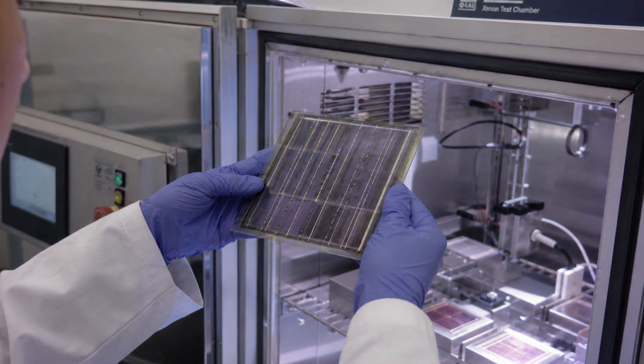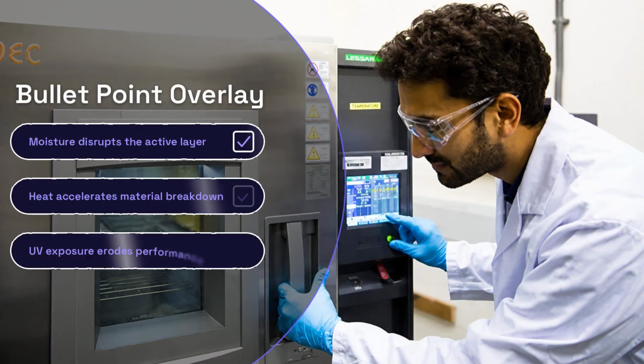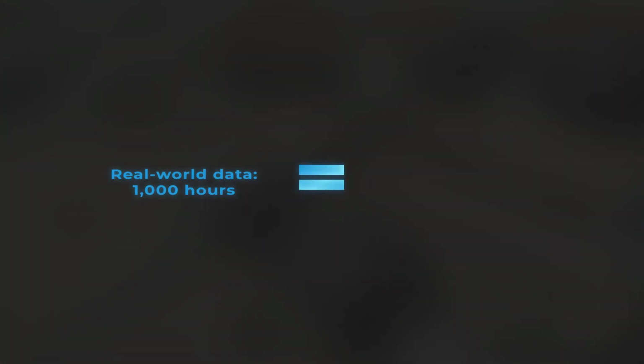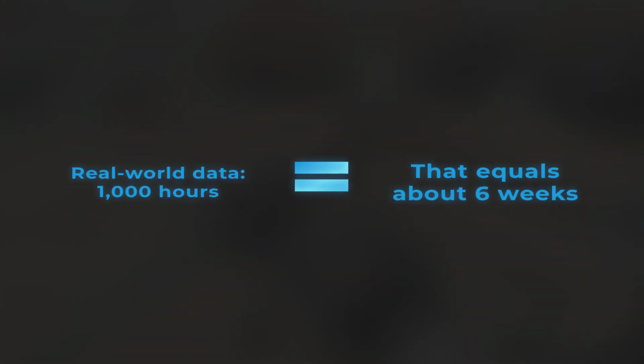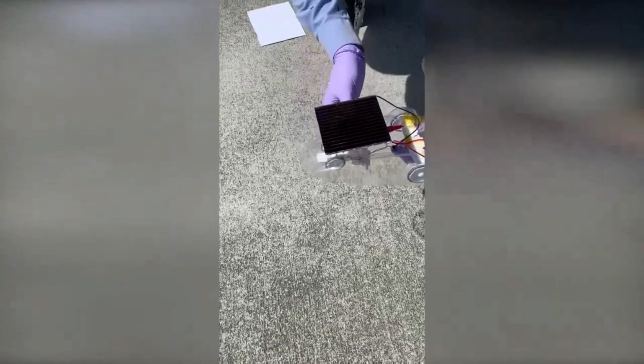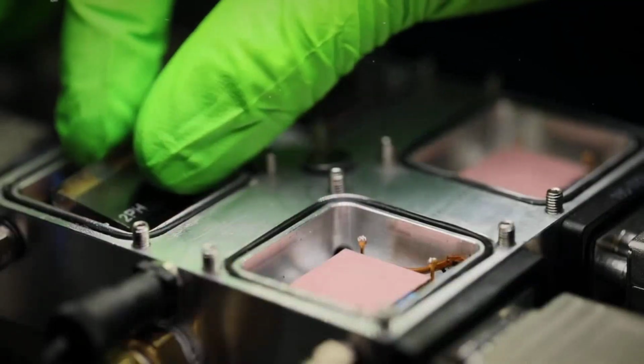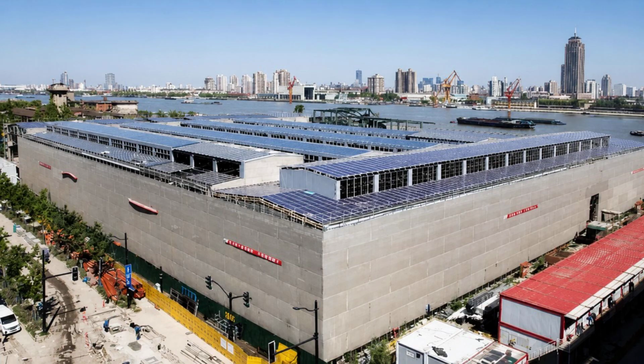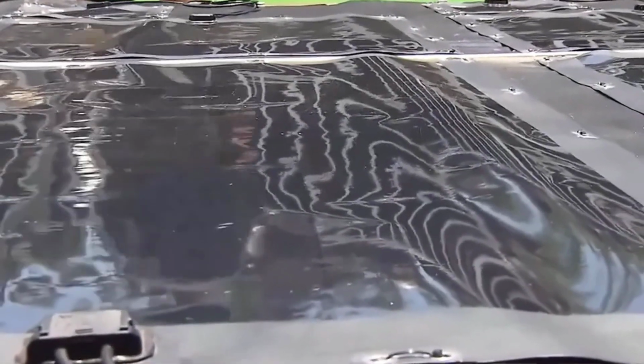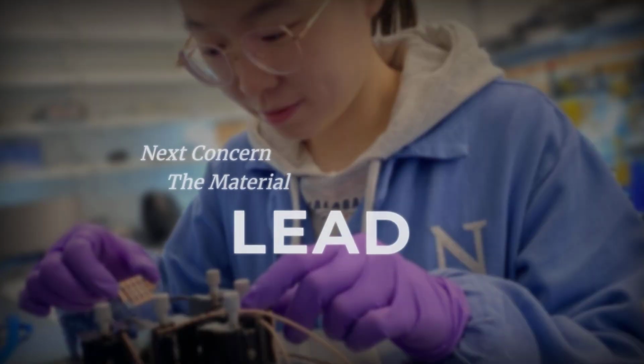First, and this is the big one, perovskite degrades when exposed to moisture, heat, and ultraviolet light. The longest publicly reported operating data for these modules in real conditions is around 1,000 hours. That's about 6 weeks. And they're being sold with 25-year warranties. Modules are passing accelerated stress tests, but an accelerated test is a simulation. Nobody has 25 years of real rooftop data because the technology hasn't existed that long.